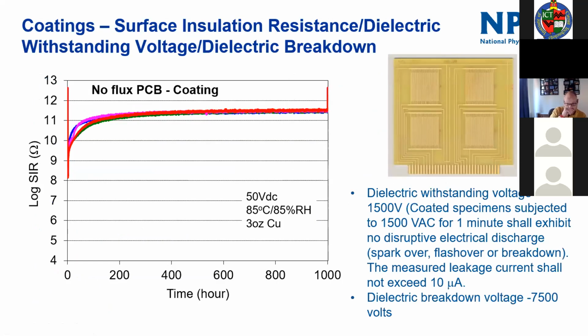What we've also done is taken some samples that we've been doing fairly standard SIR testing on. So this is a standard test vehicle that we call our TB33, but it's very similar to the B24 test pattern. And we've coated it with a normal, industrial standard conformal coating. No names, no pack drill. We've aged it in a normal SIR test at 50 volts DC, both measurement and conditioning, in an 85 environment for 1,000 hours, and you can see that the SIR holds up above 10 to the 11 throughout that test. There's no flux on this PCB.